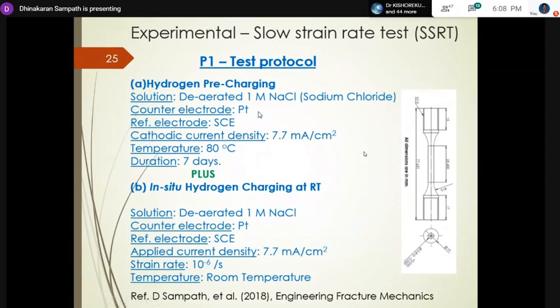Since nickel alloy is face-centered cubic (FCC) material, it will have low diffusivity. Even after 7 days, with this diameter of 3.81 millimeters, the hydrogen will reach only an annular radius of about 200 microns roughly. So it takes longer. That's the reason why they think these are good materials for hydrogen service, but still they are not. They have their own problems.